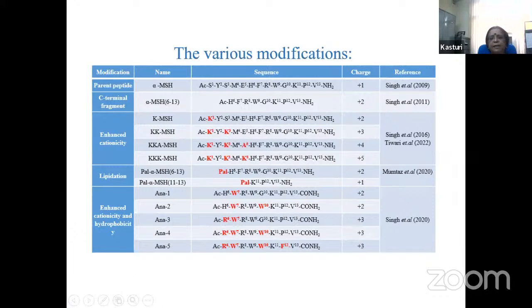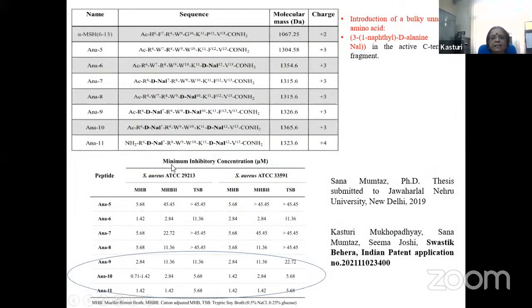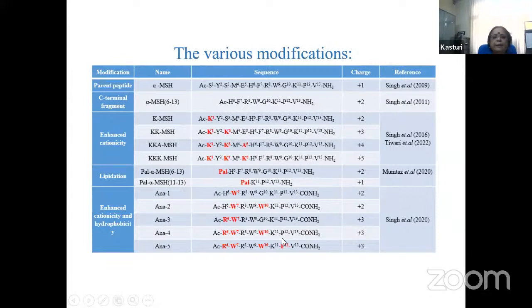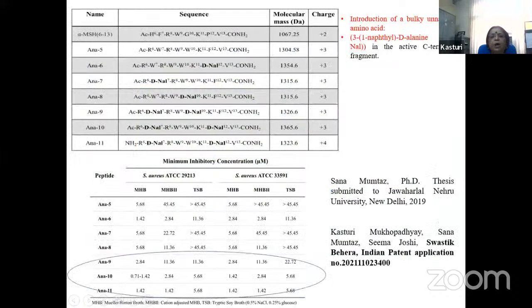modification. If you see, I'm showing a recent modification. Basically, here is a cationic charge enhancement, and this is the enhancement of the cationic charge and hydrophobicity. Then stability is an issue, so to improve the stability we introduced some unnatural amino acids.